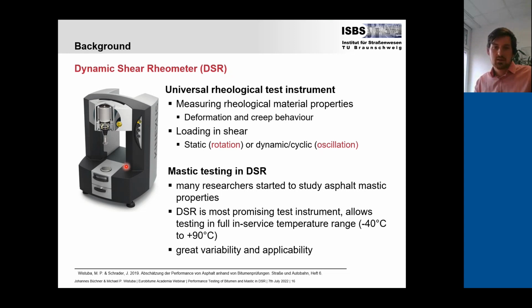And there is a possibility to perform mastic testing in the DSR, and many researchers have already started to perform and publish such tests, especially in Europe, but also in the US and in other countries. The DSR is the most promising test instrument because it allows testing in the full in-service temperature range, from -40 to +90, with a great variability and applicability of the chosen test parameters.